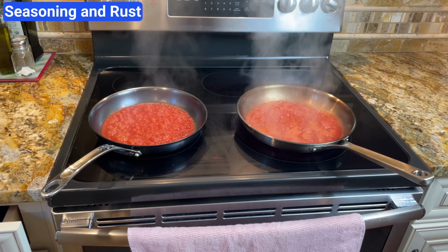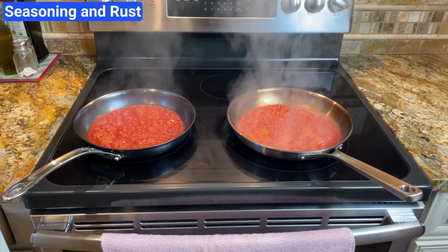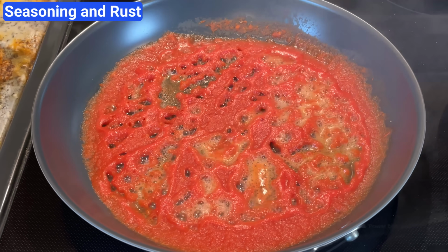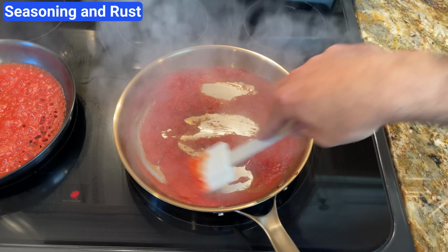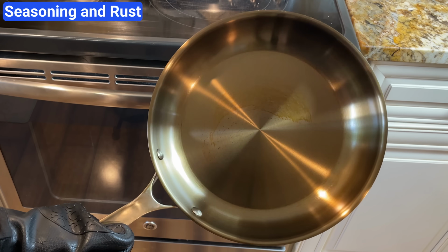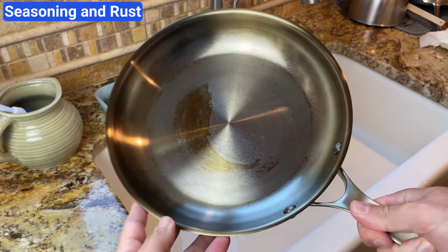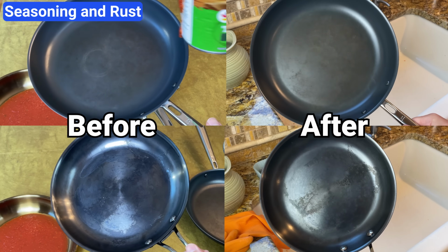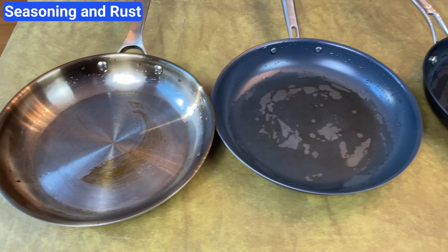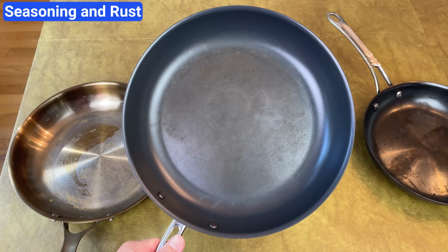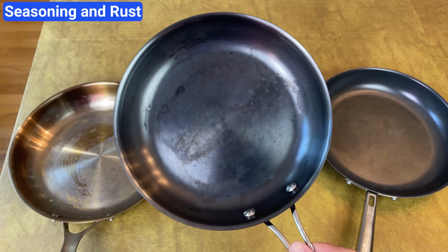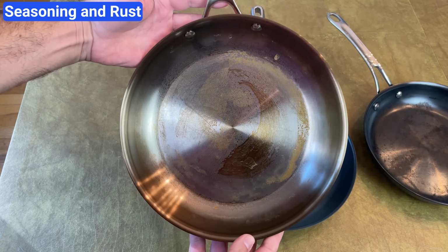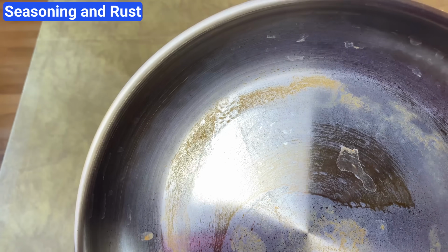Next, I simmered crushed tomatoes in each pan for 15 minutes. Acidic foods usually break down seasoning, and that's exactly what happened with Strata. Its surface went from dark and seasoned to light and patchy. Misen and Anolon were unchanged. After that, I repeated the overnight water test. Again, Misen and Anolon showed no rust. But since the tomato sauce had stripped away Strata's seasoning layer, it came back rusty.